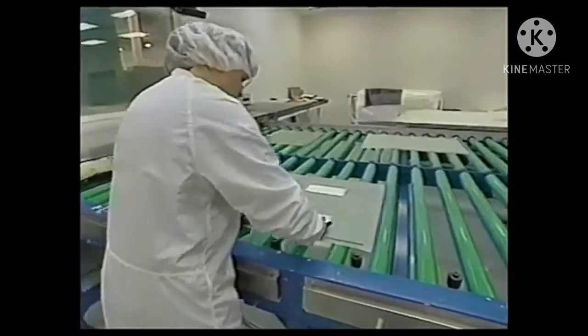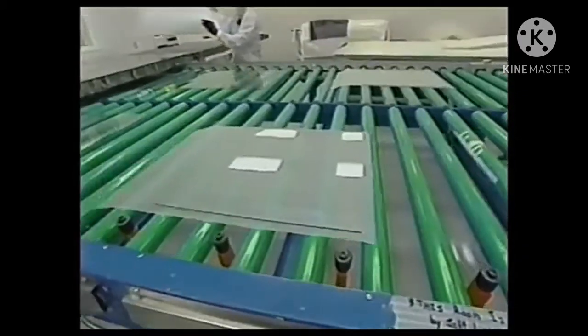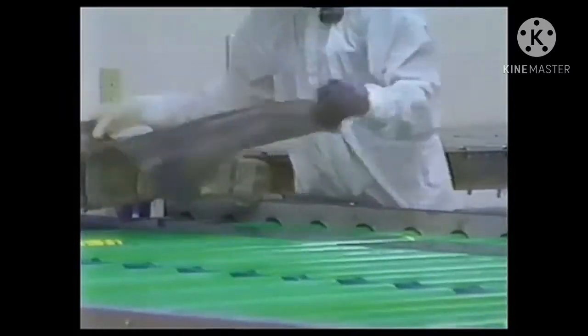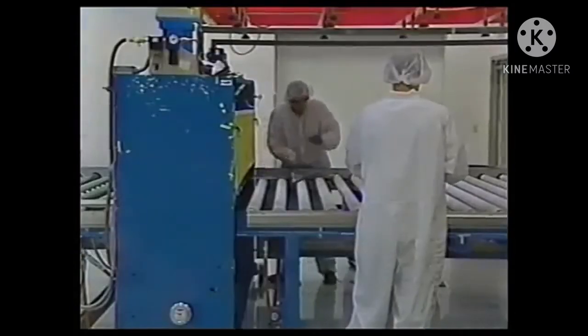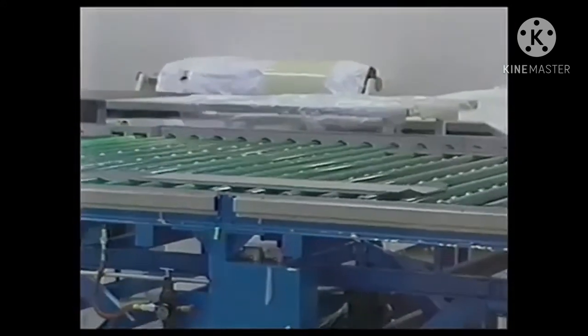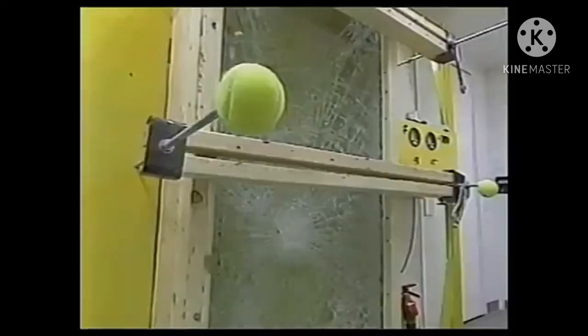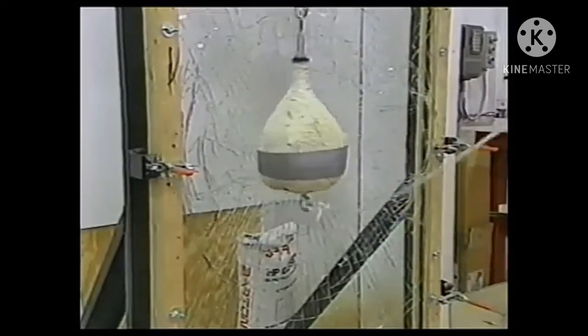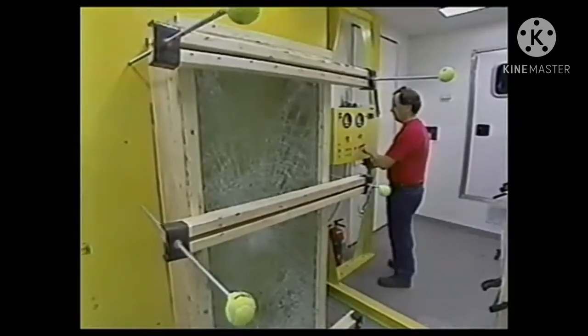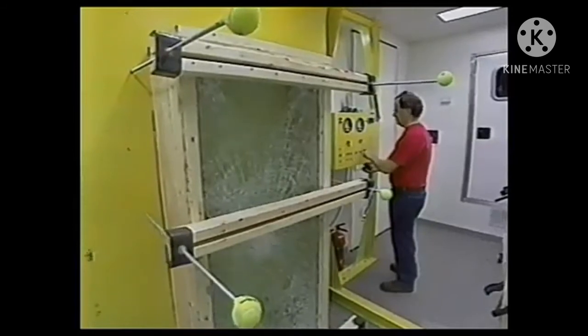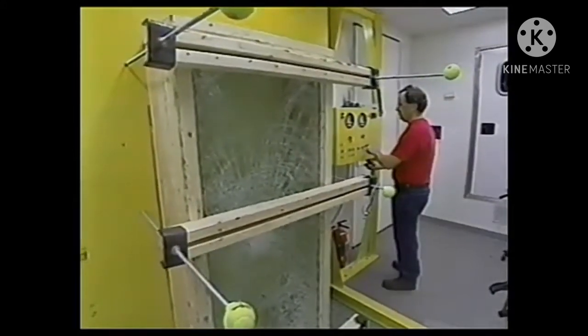Laminated glass is produced when two or more lights of glass and one or more interlayers of safety bonding material are permanently bonded together under heat and pressure. An oven is used to permanently attach the glass to the bonding material. A second heating cycle finishes the process. The principal benefit of laminated glass is performance under impact. For example, when a rock hits the windshield of a car, a laminated glass windshield may fracture, but any broken fragments will remain firmly bonded to the interlayer. Laminated glass also provides added sound control. It also blocks over 99% of ultraviolet light. Again, its most important characteristic is the ability of the interlayer to support and hold the glass when broken.